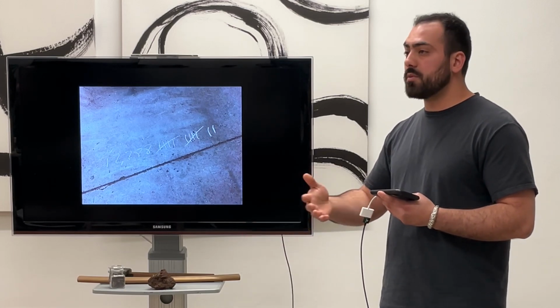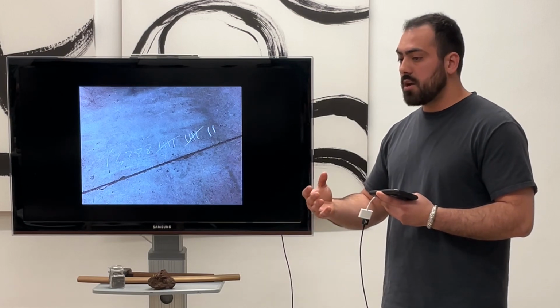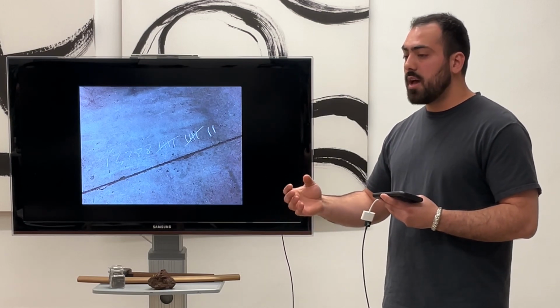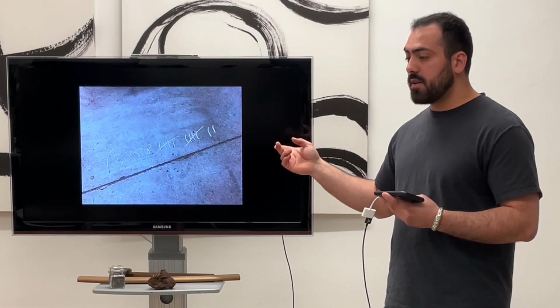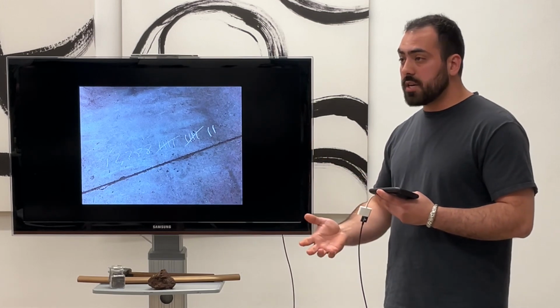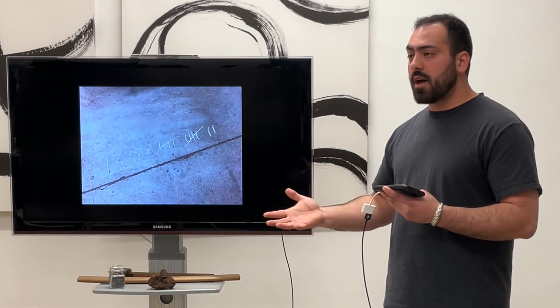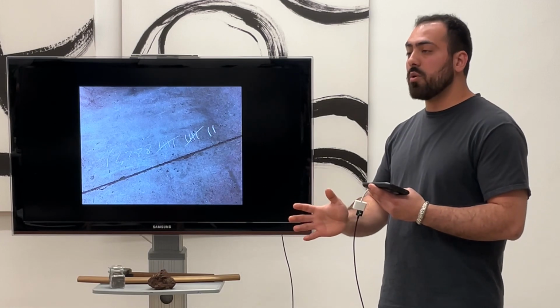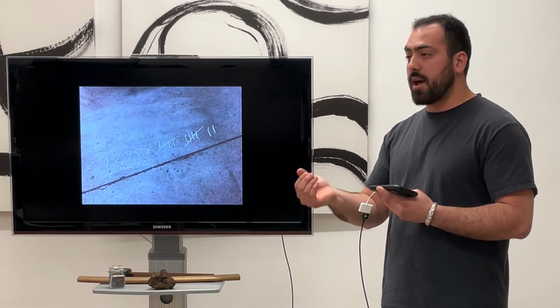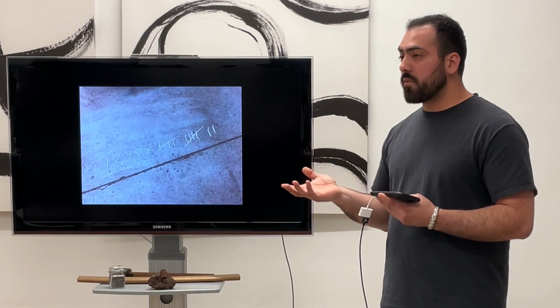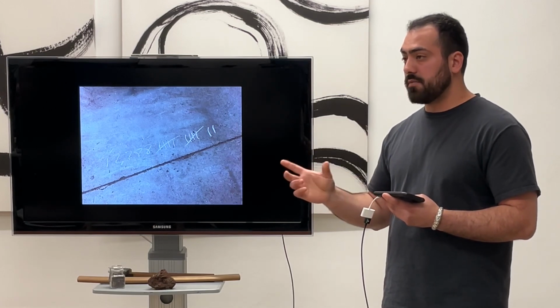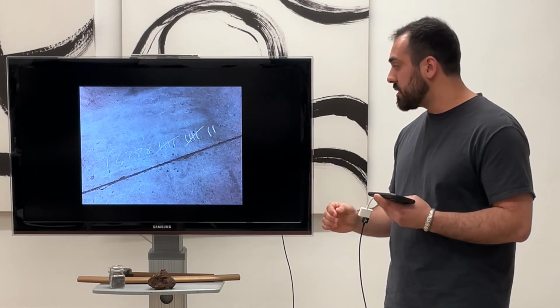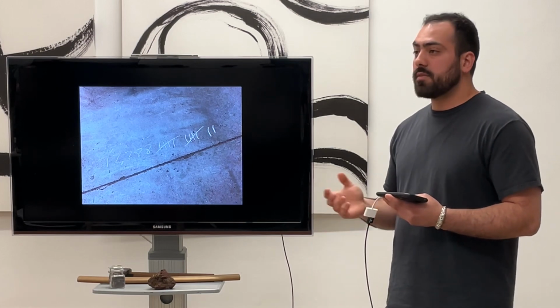So if I wanted to do kobuse or honsanmai or any of those more complex constructions, I would probably take a bar of this stuff, carburize it to a lower degree, fold it a similar amount of times, and then use that as the core with a high carbon jacket wrapped around it. I've done that before. The piece ended up having a flaw in the steel, so it was never finished. It's just a different way of approaching it.